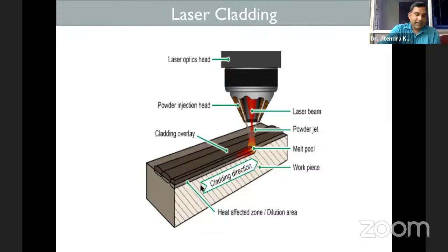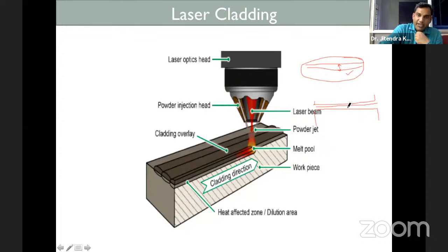So in laser cladding, how can you remove the distortion defect? Because at that high temperature, what happens? This is the straight plate over the surface. You solidify it, then it can be a little bit distorted, so the edge is distorted. This is not desirable. This can also be removed by adding a buffer layer between the coating. So this is your top surface coating, this is the buffer layer, and this is the bottom substrate. If you use the buffer layer between the coating and the substrate, then you can reduce this distortion effect. Also, you can improve the bonding strength between the coating and the substrate. That's why the importance of the buffer layer is very much.